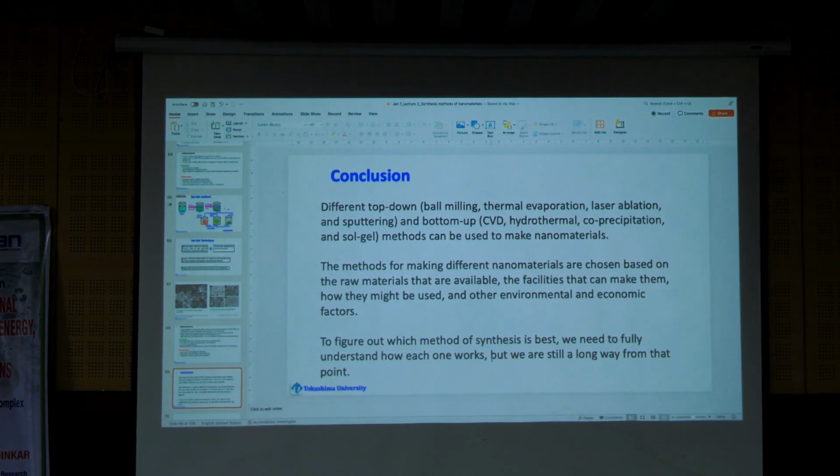The diameter should be very fine, like less than maybe 0.1 micrometer, so that the reaction occurs in a small area. If the beam is very big, it will affect a large area, so small particles will not be generated. In case of nanosecond pulses, a large plasma is created. In case of femtosecond pulses, a small area. So with femto, the size is 5 nanometer.